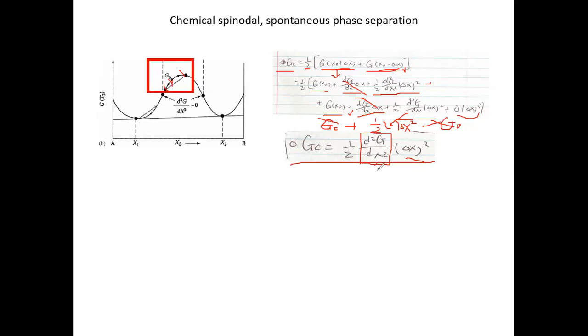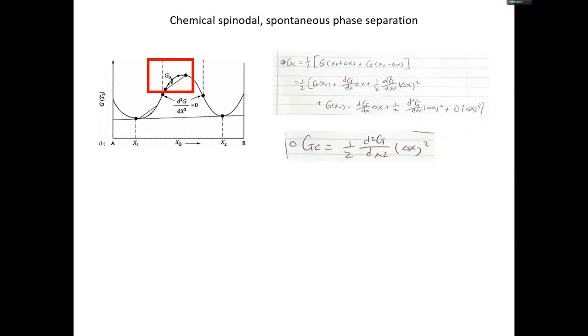And mathematically now you can see when this guy is negative, which means that we're in this concave part, we have a reduction of free energy. So go ahead, do the transformation. And when the original composition is in this convex branch, this part is going to be positive. So you're doomed. You cannot do that transformation because it's going to give you such an increase of the free energy. Basically, again, using the rigorous thermodynamic considerations, we reach exactly the same conclusion from our geometrical illustration.